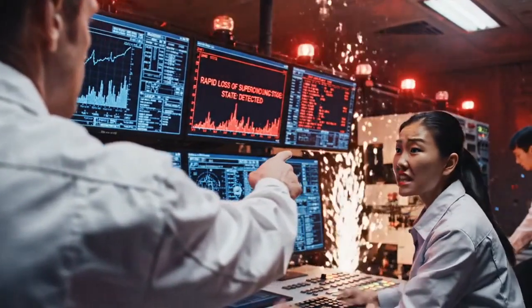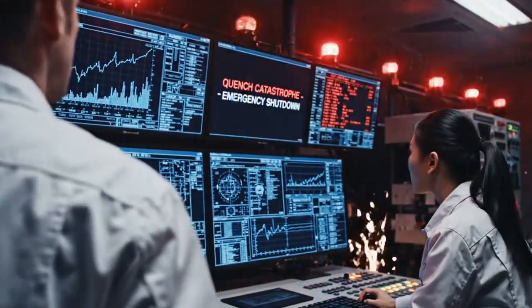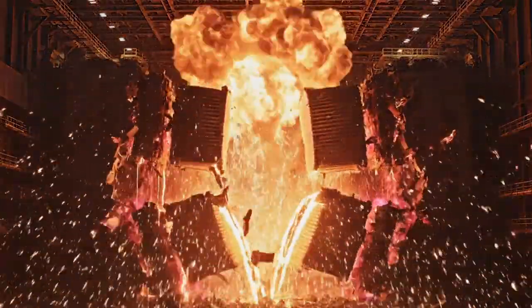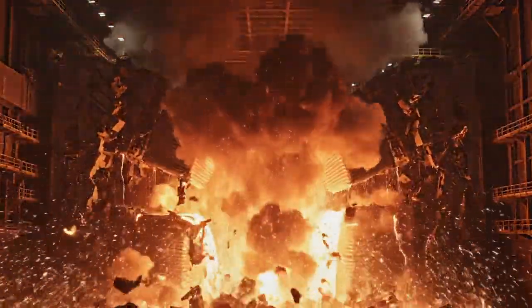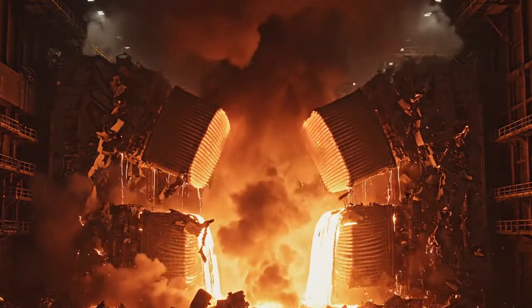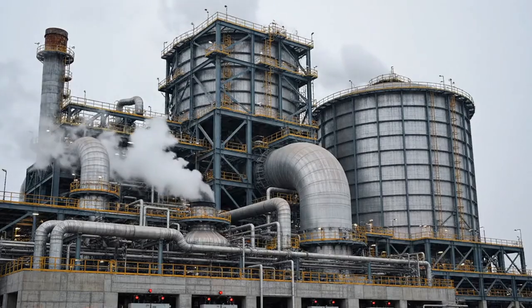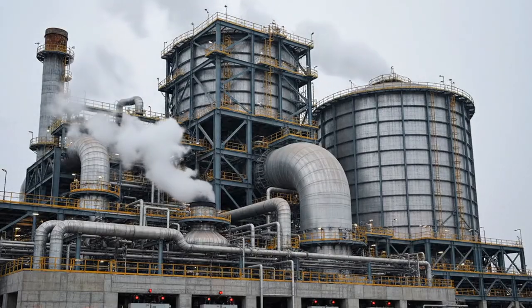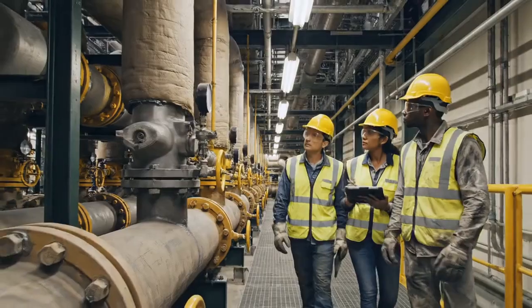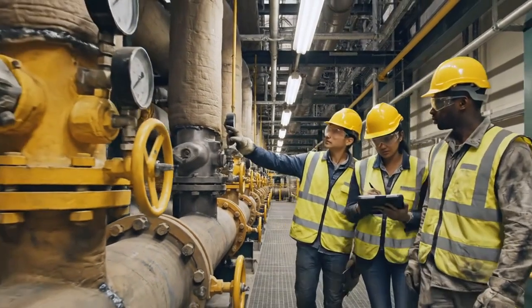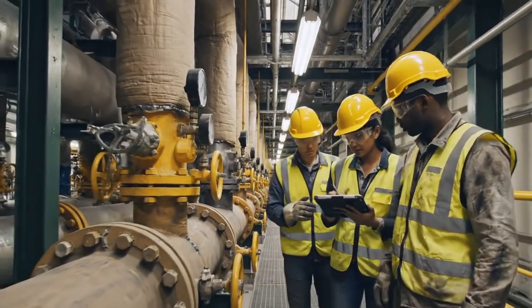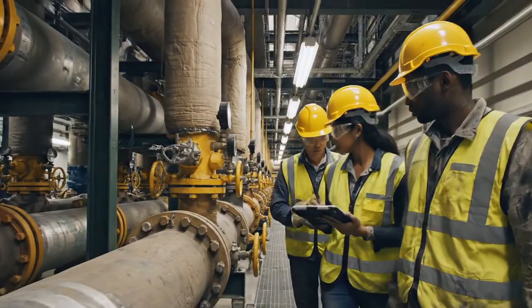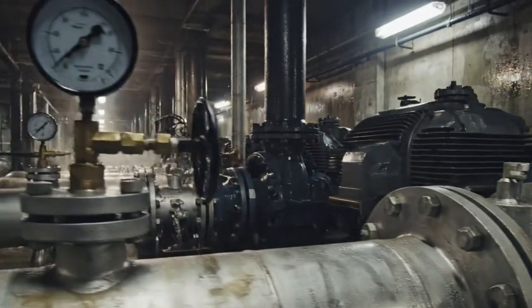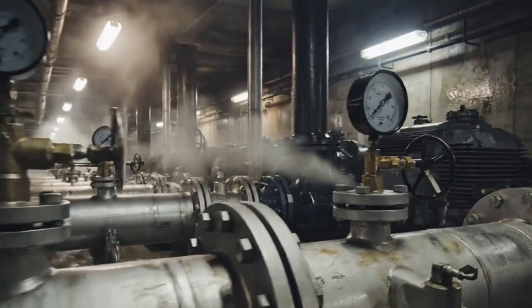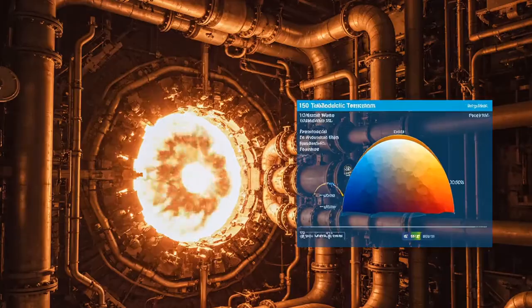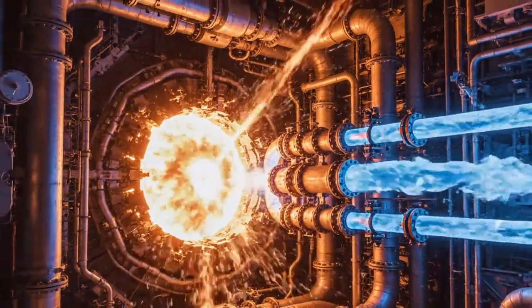A quench is a catastrophic failure mode where the wire rapidly loses its superconducting state, violently converting the stored magnetic energy into raw thermal heat, potentially warping or destroying the multi-billion-dollar coils. Aside from the cryoplant, the heat rejection system for the divertor and the vacuum vessel is equally massive. The tokamak cooling water system is an intricate industrial plumbing network consisting of over 36 kilometers of nuclear-grade piping. This pressurized system must circulate up to 33,000 cubic meters of highly purified water per day to capture the immense thermal energy radiating from the plasma core.